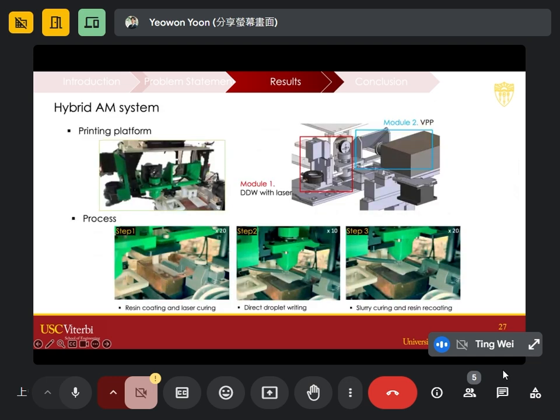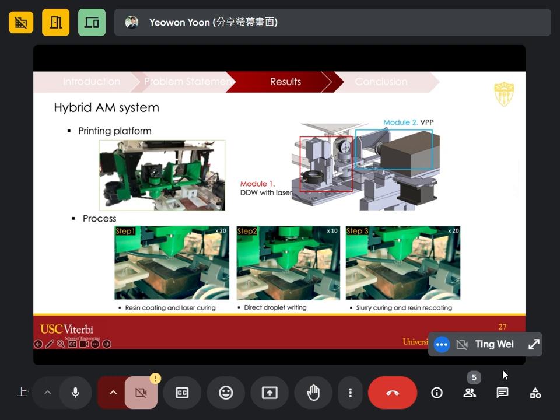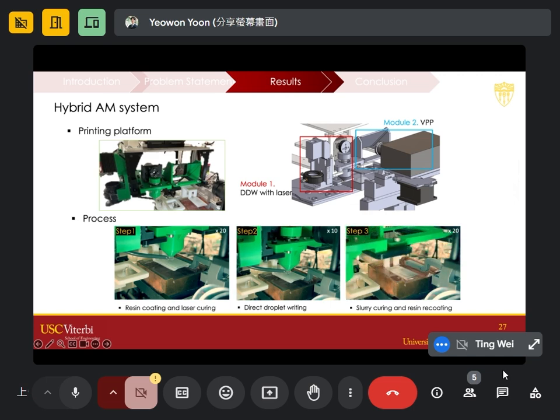So this is the machine setup that we have in the lab. It looks very complicated, but in a nutshell, it's only two parts: the direct writing nozzle with the laser, and the secondary module for the resin print. The first step is the resin coating, and then a secondary laser comes and cures the whole layer, creating a very dry surface for material transfer. The second step is droplet writing. You can see this spring motion going up and down to plunge and push the material onto the substrate. Finally, step 3 is to cure this with the laser, and then it goes in and recoats the resin to print another layer on top of this one. Here, I print 2 more layers, and then the print is finished.